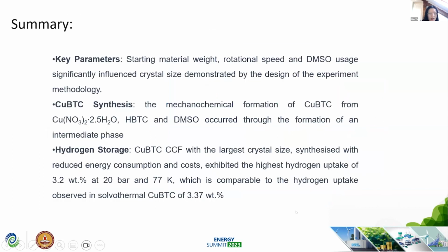So, as a summary, through the design of experiments methodology, we can clarify that the starting material weight, rotational speed, and the DMSO usage can significantly influence the crystal size. In addition, we found in the copper BTC synthesis procedure that the mechanochemical formation of copper BTC from copper nitrate, H3BTC, and DMSO occurs through the formation of an intermediate phase. In addition, the hydrogen storage shows that the copper BTC with the largest crystal size, synthesized with reduced energy consumption and cost, exhibits larger hydrogen storage, comparable to the hydrogen uptake observed in solvothermal copper BTC.